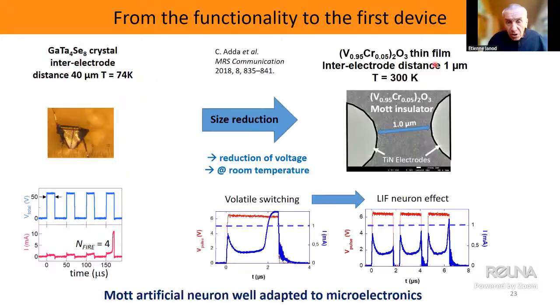But what we have shown is that after downscaling and using no longer crystals but thin films, you see here a view where on the right and on the left you have the electrodes. If we downscale this quite a lot, the inter-electrode distance is now 1 micron, and we can go lower than that now. You see that we have a strong reduction of the operating voltage. And on the other hand, these devices are working at room temperature. So we have the proof of principle that Mott artificial neurons are well adapted to the constraints of microelectronics.